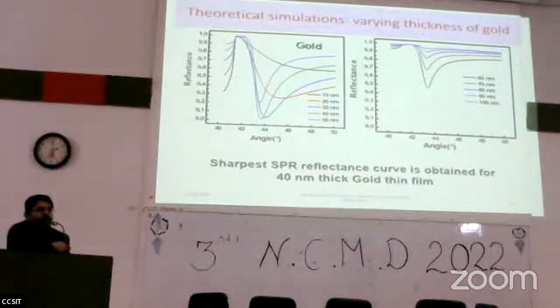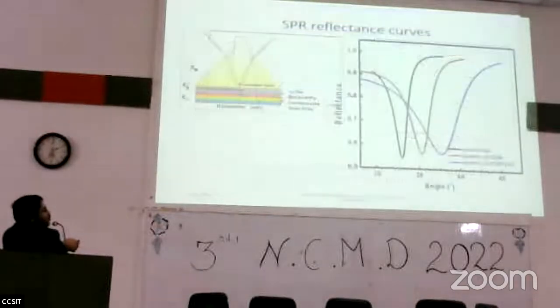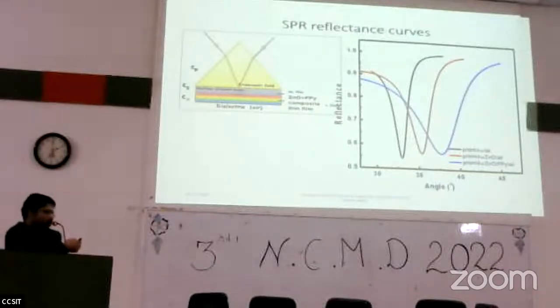So first we vary the thickness of the gold metal. As you can see, the sharpest curve, or minimum reflectance, was observed for 40 nanometer thickness of metal. So this is the optimized thickness for the gold film. This is the step by step SPR curve for three layers: first using only the gold film, then zinc oxide with air as dielectric, and then the polypyrrole composite on it. As we can see, the resonance angle goes on shifting and increasing, and the minimum reflectance values also change.